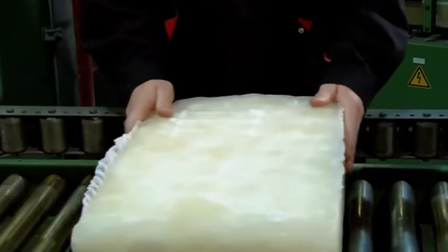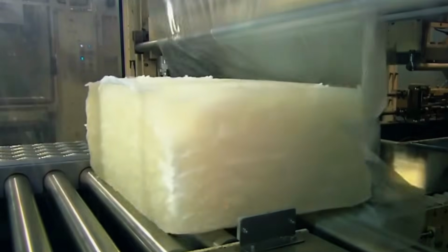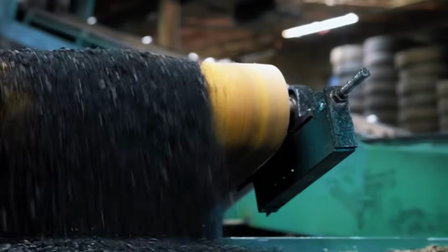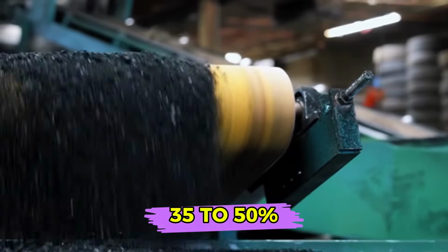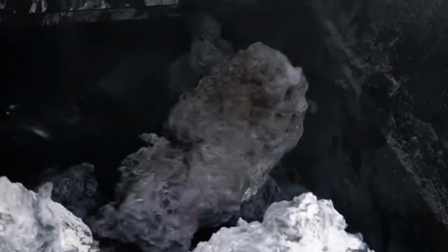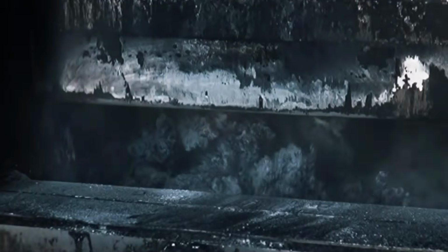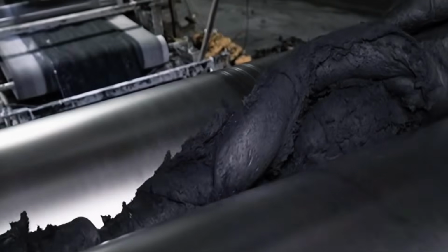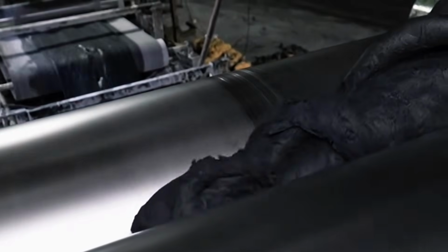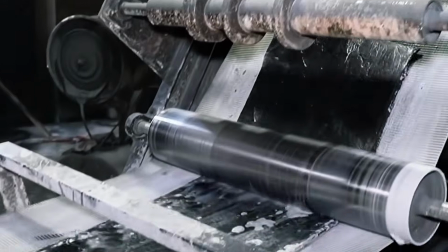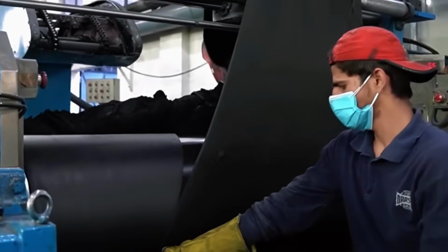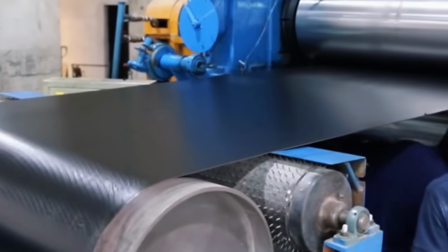In the compounding room, both types are blended together. In an aircraft tire, natural rubber makes up 70 to 90% of the total content. Carbon black is added at 35 to 50% relative to the rubber by weight. It is also what turns rubber from off-white and soft into the tough black material on every aircraft tire. Process oils, sulfur, accelerators, and anti-aging agents are added in precisely measured amounts. Everything goes into a high-speed internal mixer. The compound that comes out is not just rubber, it is an engineered material designed to perform at extremes that would destroy anything less. But the compound is only the skin.